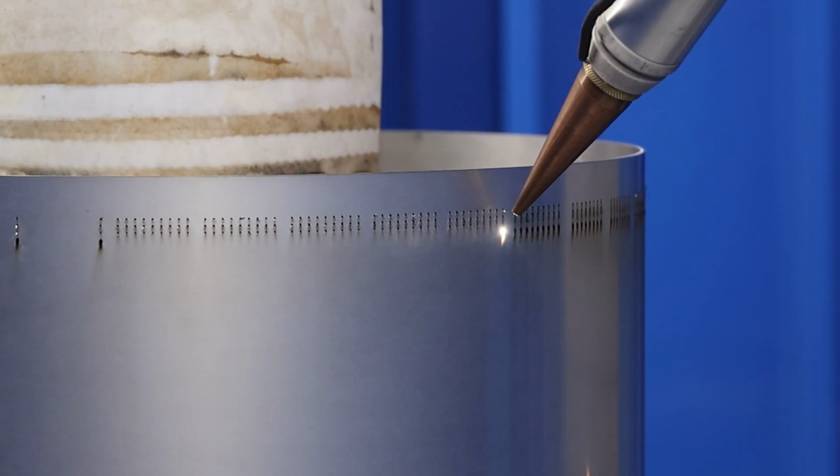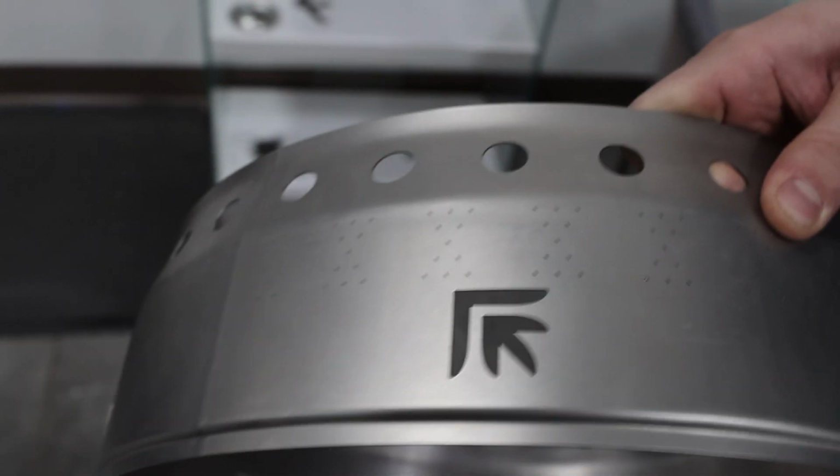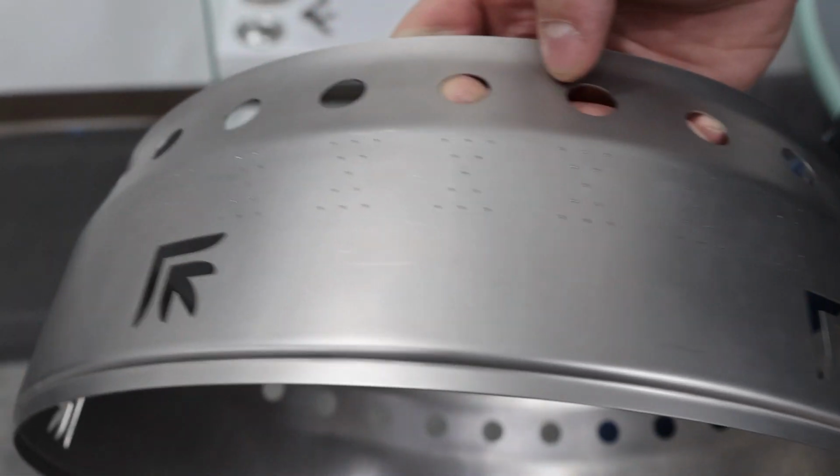When you're talking about drilling with these lasers, it's a lot of aerospace drilling. So when you talk about planes flying over your head, a lot of the drilling the holes in those combustors that make the planes fly, doing these blade and vanes, part of the combustor that makes the engine run, things like that. That's really small, tiny holes. I mean, you're talking 1 millimeter thick, 0.5 millimeter diameter holes that you're trying to drill through 20 millimeters of material.